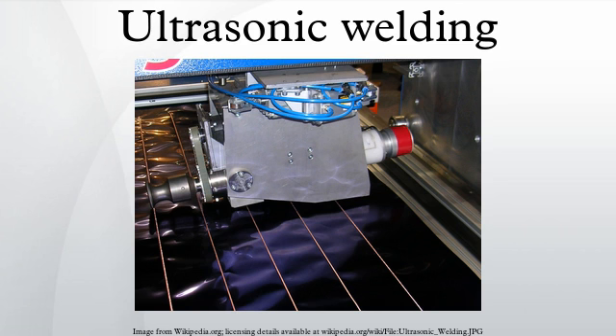The interface of the two parts is specially designed to concentrate the melting process. One of the materials usually has a spiked energy director which contacts the second plastic part. The ultrasonic energy melts the point contact between the parts, creating a joint. This process is a good automated alternative to glue, screws or snap-fit designs.